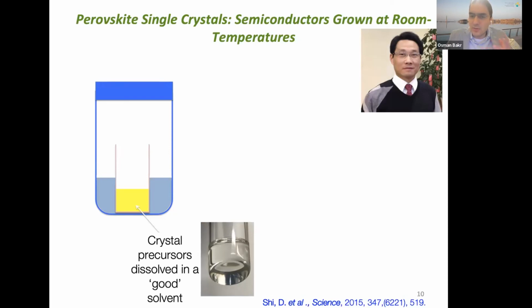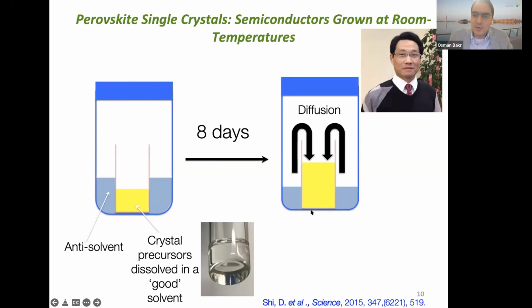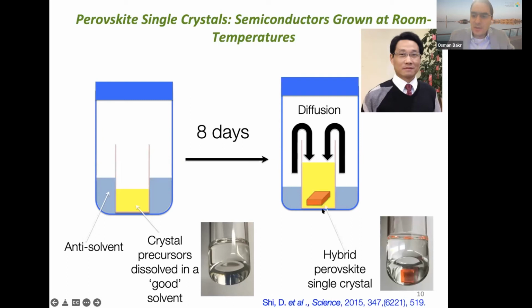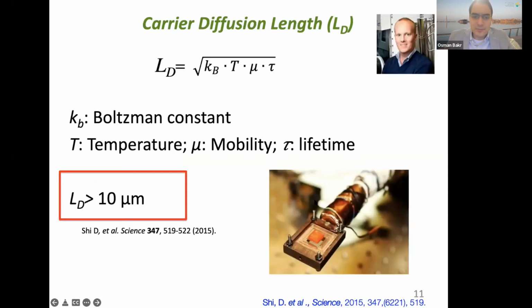One of the simplest methods we developed was basically growing perovskites from a good solution and storing the solution in a bad solvent, and over the matter of a few days to a week, you get diffusion of the bad solvent into the good solvent, supersaturation of the perovskite solution, and you start seeing a crystal grow. What makes perovskites different is that the single crystal that grows is actually quite large. Normally, when you grow crystals with this method, you get very tiny crystals.